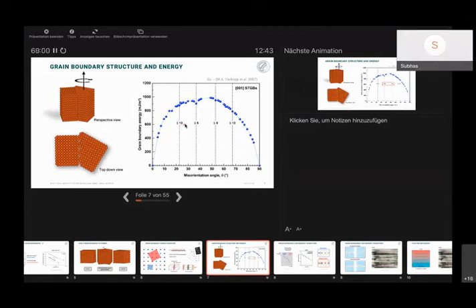Yeah, it makes clear. There is another sigma 5 boundary between 30 to 40 degrees. Yes. That also we can make by arranging 30 to 40. Yes. So that is now a good question. As I said, the one is a 210 and the other one is a 310 grain boundary, and the structure is very, very similar. I have never tried to grow both of them and see how they form. But in theory, exactly, if you rotate by 54 degrees, you should form the one variant. And if you rotate by 36 degrees, you should form the other one, in theory. But I've never tried it experimentally.